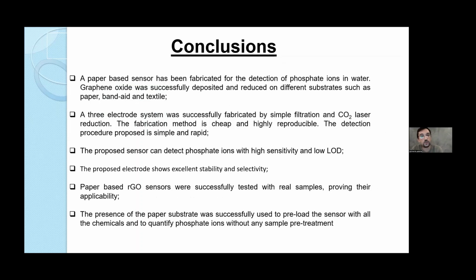And the proposed sensor can detect phosphate ions with high sensitivity and low limit of detection, with excellent stability and selectivity. And the paper-based reduced graphene oxide sensors were successfully tested with real samples, proving their applicability. And the paper substrate was used to preload the sensor with all the chemicals and to quantify phosphate ions without any sample pretreatment, so enabling real-time and in-situ analysis.